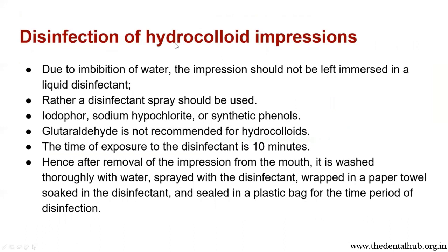Hydrocolloid impressions include both agar and alginate. Due to the properties of imbibition and syneresis, the impression should not be left immersed in liquid disinfectant; rather, a spray should be used. Acceptable disinfectants include iodophore, sodium hypochlorite, or synthetic phenols. Glutaraldehyde is not recommended for hydrocolloids. The time of exposure is 10 minutes. After removal of the impression from the mouth, it is washed thoroughly with water, sprayed with disinfectant, wrapped in a paper towel, soaked in disinfectant, and sealed in a plastic bag for the disinfection period.